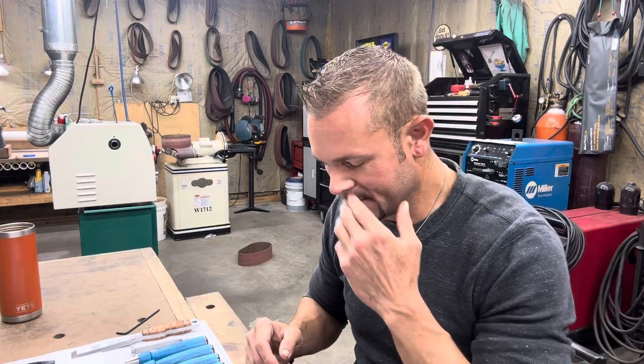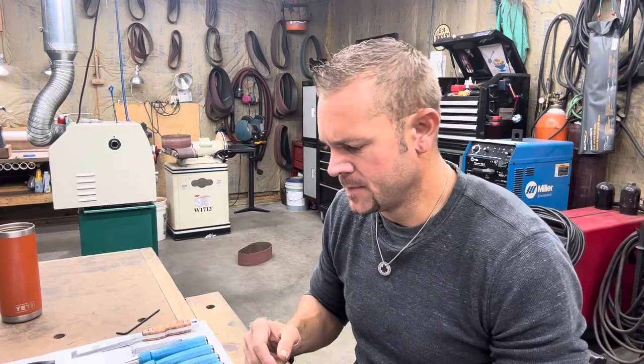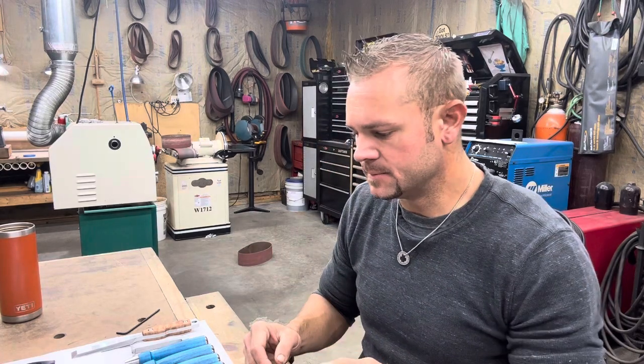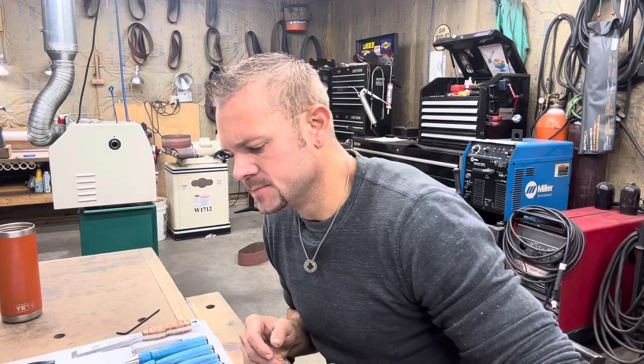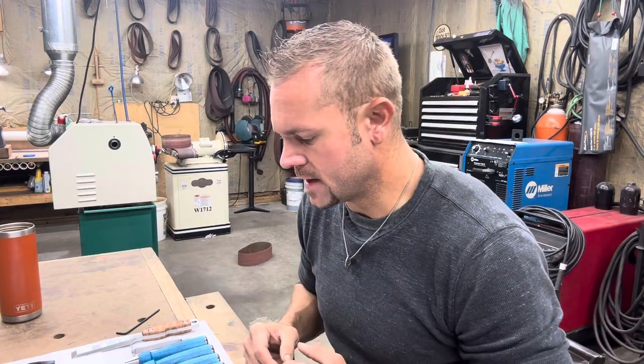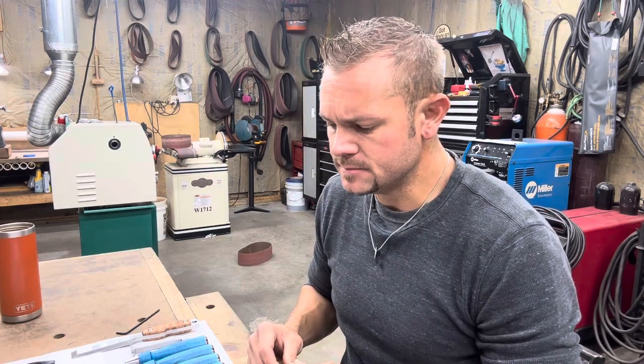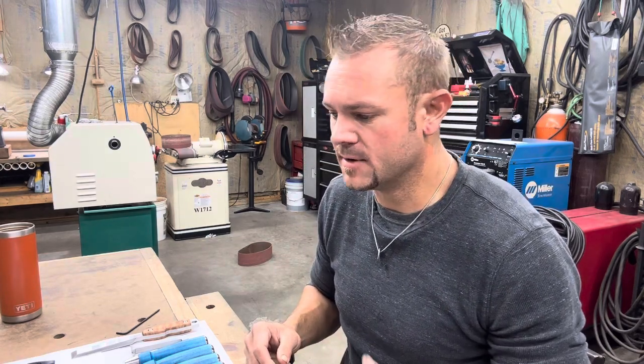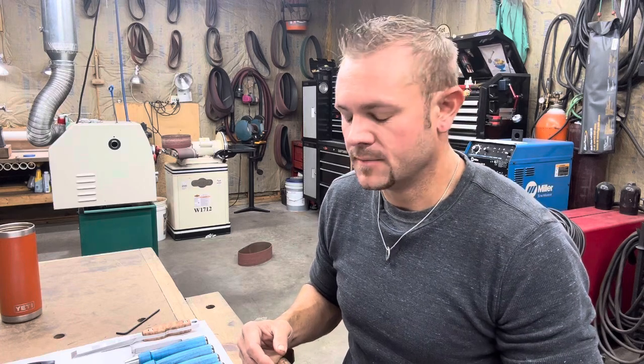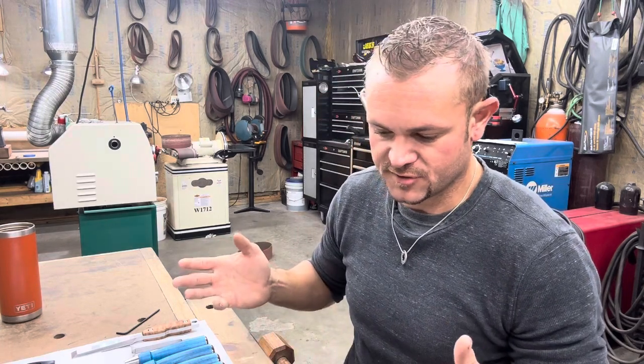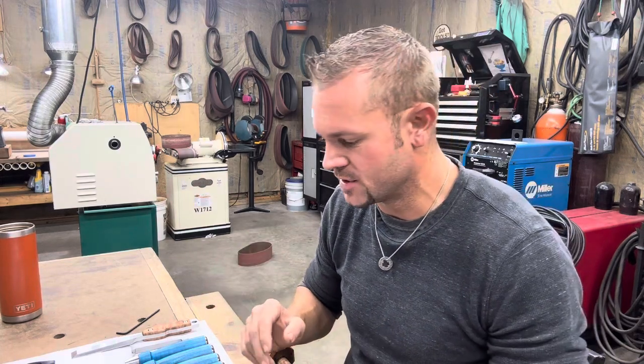There are materials out there that are designed to be water quenched. For example, W1 and alloys I don't even work with, but there are water quenched alloys. And then you move up to oil quenched alloys. Then you move up to air hardening alloys and stuff like that, to where they need different rates of cooling. And generally speaking, with higher alloy steels with higher carbon, you can oil quench them, but you can also air quench them. The only difference is you're going to end up with varying levels of retained austenite. And that's as far as I can go without getting into my particular heat treatment procedures,